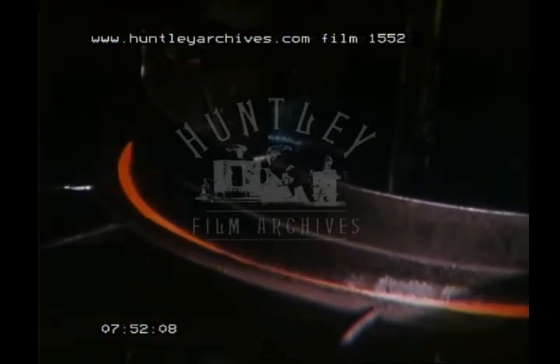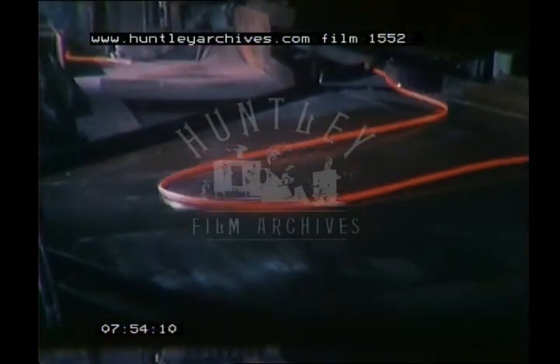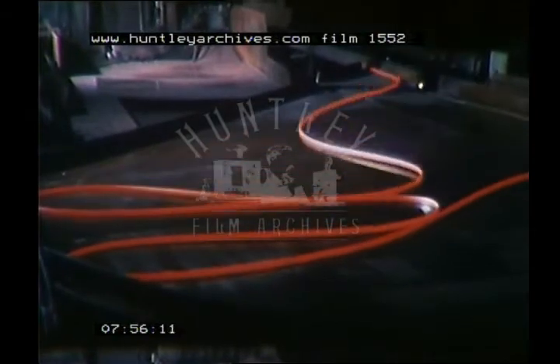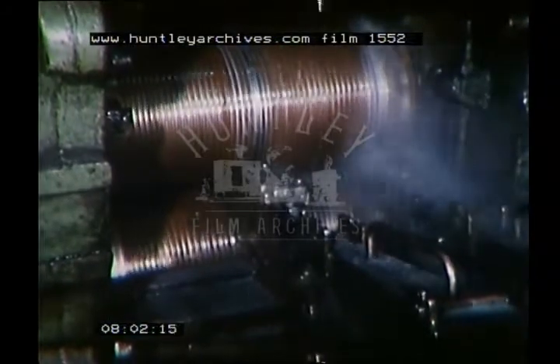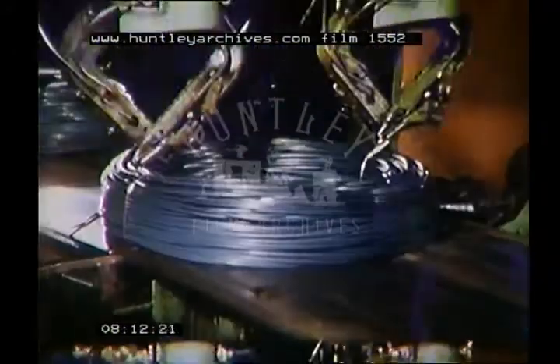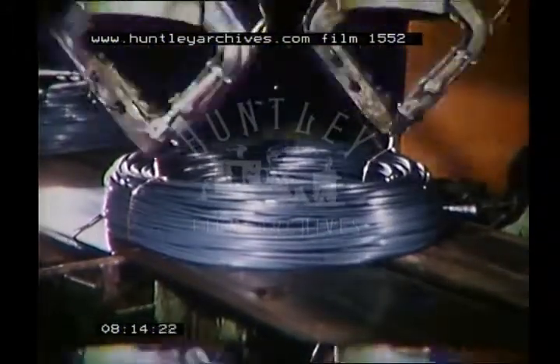However, when the tremendous improvement in rod quality and greatly improved groove life with fewer roll changes are taken into consideration, the roll cost per ton of copper is substantially reduced. Furthermore, since the rolls are of uniform hardness throughout, the groove life remains constant over the life of the roll. Where the design permits, it is also perfectly feasible to machine a smaller roll from the scrap rolls, and so secure further life at a minimum cost.